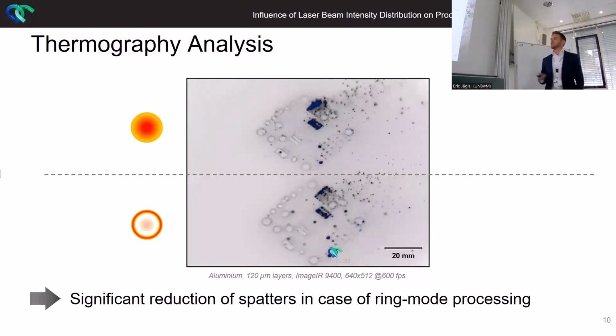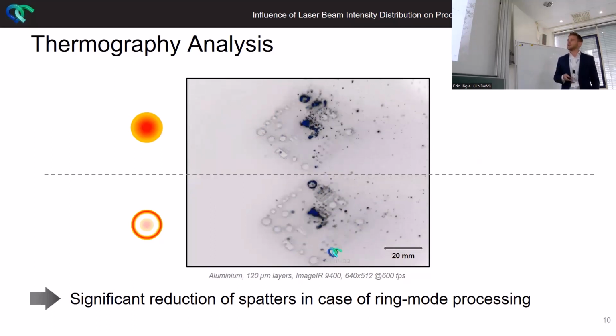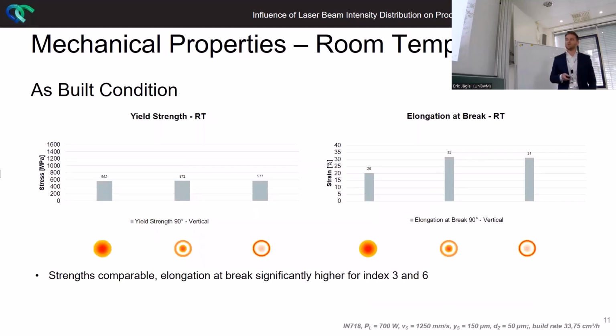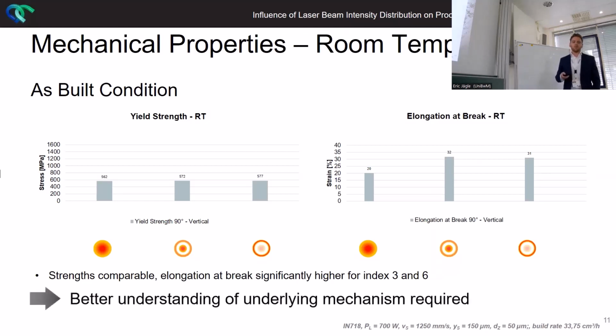That helps us a lot this way. But just as an excursus and coming back to our conventional analysis and parameter study, already the mechanical properties revealed some big differences, while we have some comparable or slightly higher yield strength for index 3 and index 6. The elongation at break was much higher for the samples of index 3 and index 6. And that was clear that we have to dive deeper into our analysis and to better understand the underlying mechanisms.